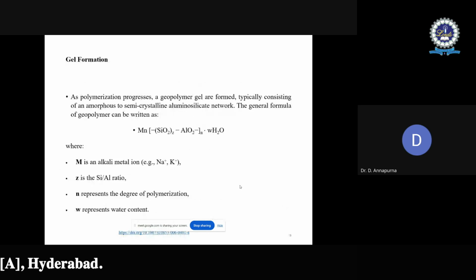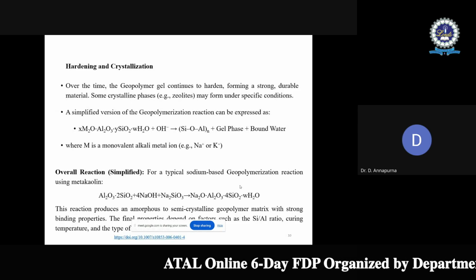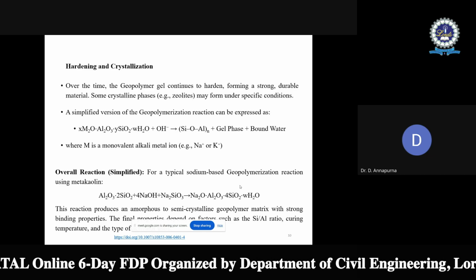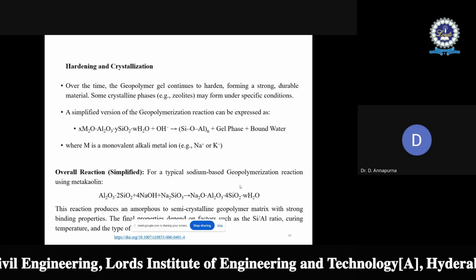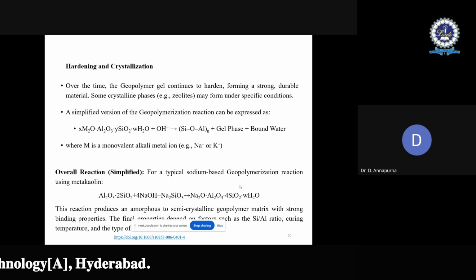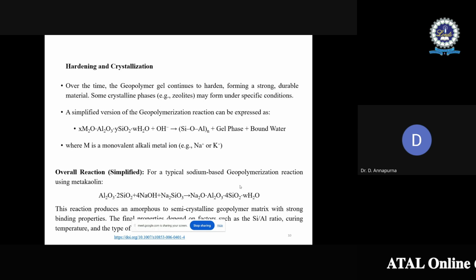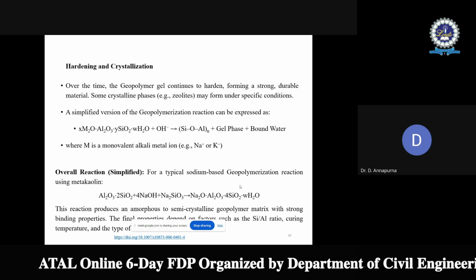First, all the precursors are going to be dissolved in the mix in the presence of this alkaline medium. The next stage will be oligomerization and polymerization. After that, gel will be formed, and the gel will be hardened and form a crystalline product. If we take silica and alumina rich materials as the precursors, then the resulting product will be N-A-S-H gel. This is, in brief, the geopolymer reaction or geopolymerization process.